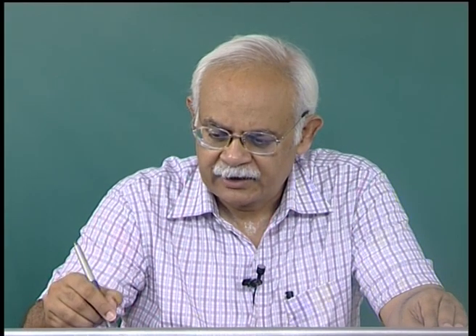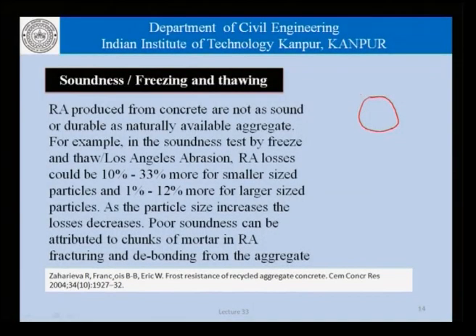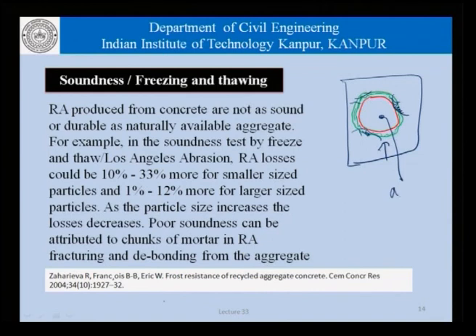See, what is really happening is that we have a normal aggregate like this, and we have some contaminant deposit on the aggregate. And once this recycled aggregate is tested, for example, in a Los Angeles abrasion kind of apparatus, it is likely that chunks of this mortar, which is adhering to the surface of this aggregate, could fracture or debond or just spall off and so on. As a result of that, the net change in weight of this recycled aggregate will be a lot more than if we were testing simply this old natural aggregate.